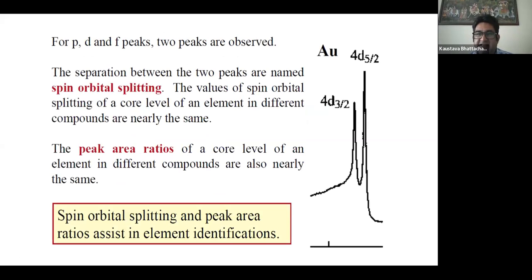Okay, so now we come to the peak splitting. We know that we have the 4 basic quantum numbers: the principal quantum number, azimuthal quantum number, magnetic quantum number, and the spin quantum number. We usually have LS coupling, that is L is coupled with S to have 2 different energies. So it can have an L plus S value and an L minus S value. That's what we call Russell-Saunders splitting. In XPS, we can find out the splitting parameter for the spin orbital splitting. That splitting parameter is an internal property of an element, so from that we can also identify that particular element.